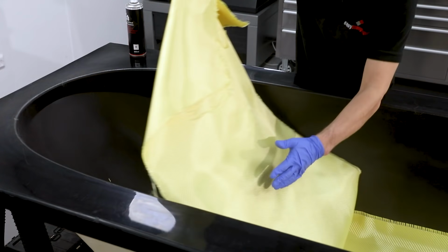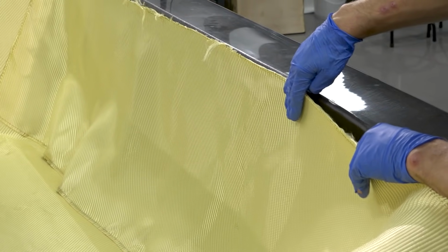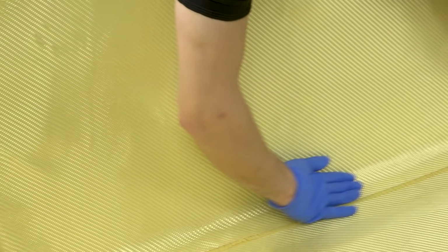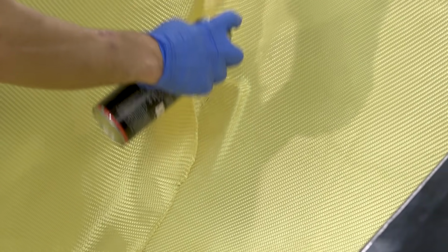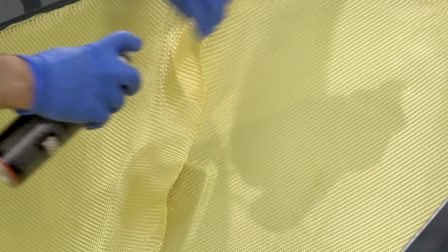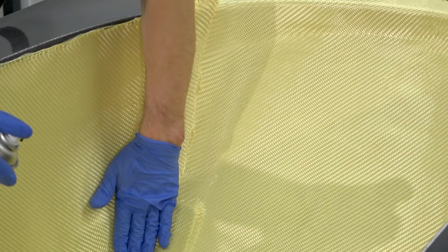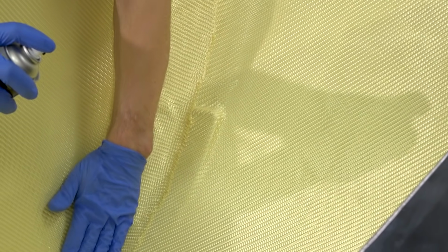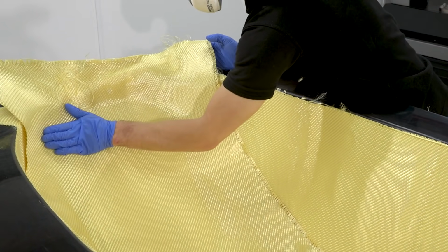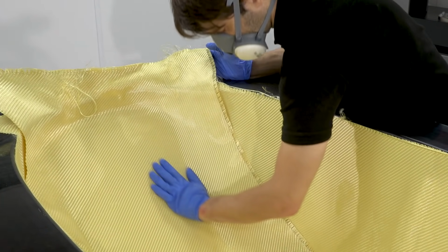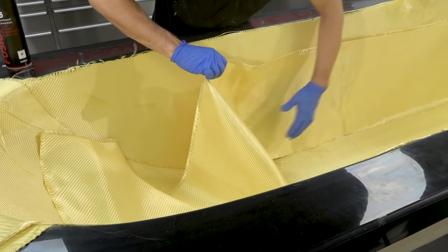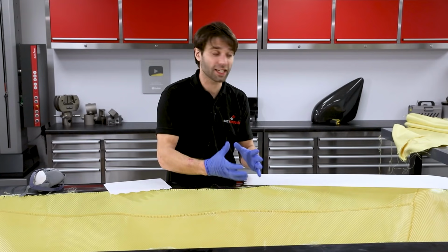When you lay the reinforcement, you need to position it as tightly into the mould as you can. This reduces the possibility of bridging in the corners and ensures consistency in the part. Joins in the reinforcement should overlap to prevent weak points. In the case of this part, we allow a fairly large overlap as we actually want the additional thickness of the join in the corner. This is where the sledge will receive most of the impacts. The second ply into the mould is simply a repeat of the first. So that's the first two plies for the outer skin laminated.